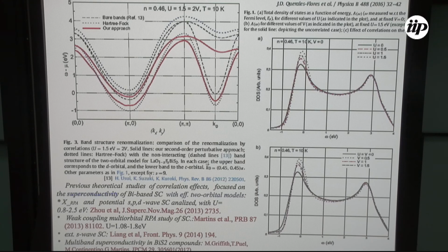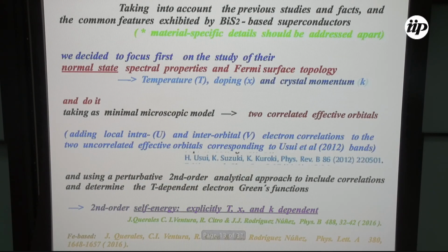correlations. And for example, what we did was, as I will quickly show here, taking into account all that was known in 2016 actually for the bands. We wanted to study these properties, so we took as a minimal microscopic model the Usui orbitals, which were uncorrelated in principle, obtained from the DFT, and then we added local correlations, intraorbital and interorbital, and analyzed the effects. How? Well, we did the Green function calculation. There is evidence from many works that the correlations are not very large, so this kind of scheme should work well, and actually it does improve the results.